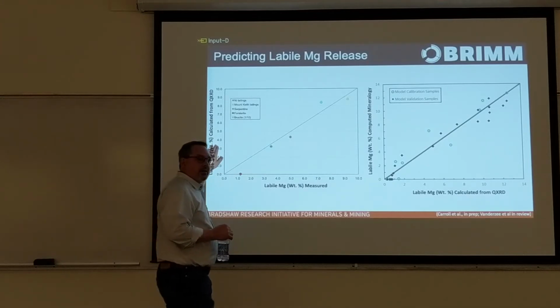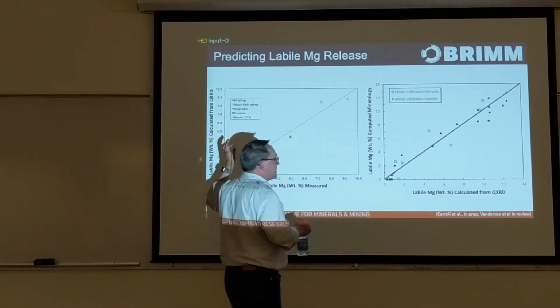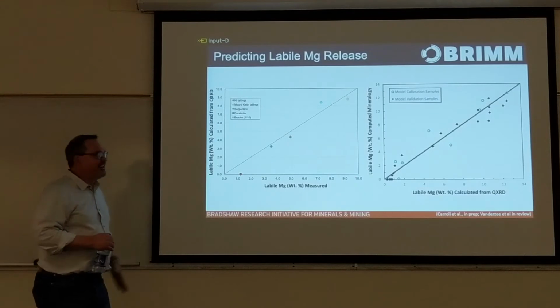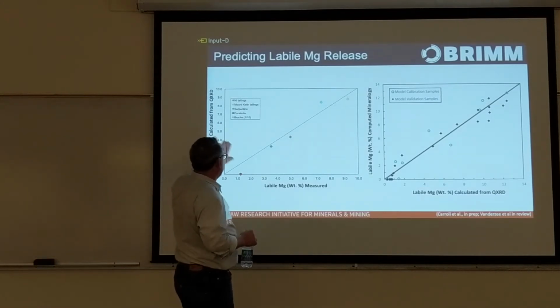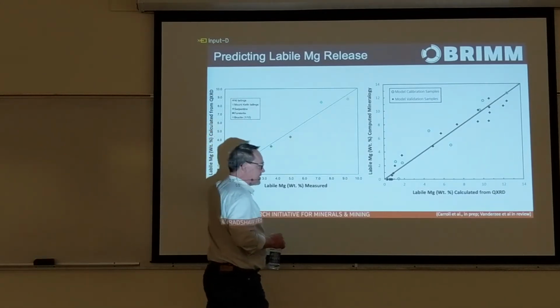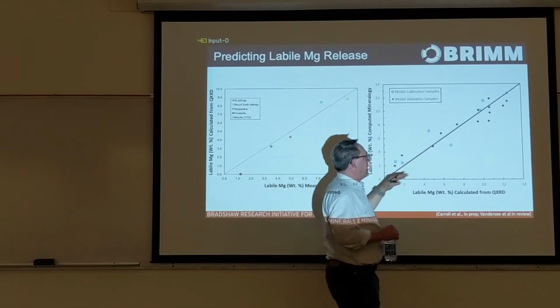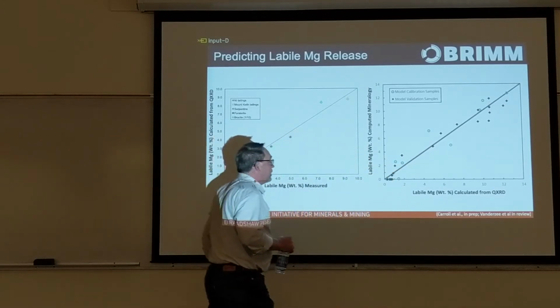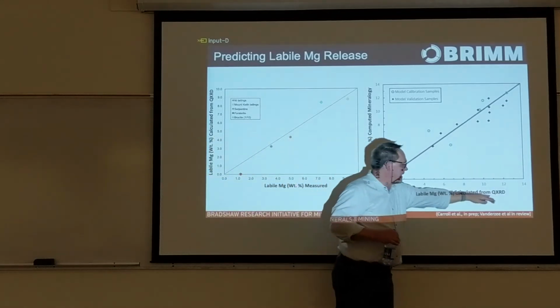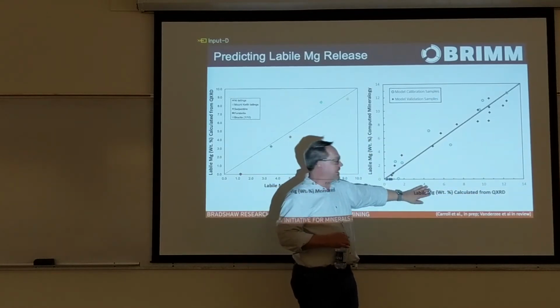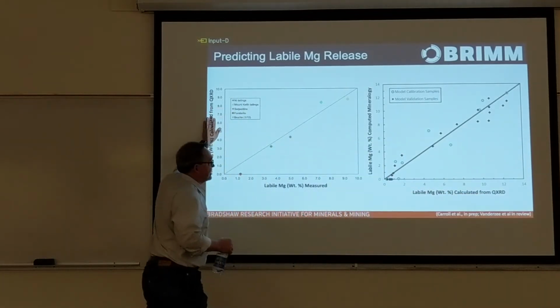That's still hard work, and Maddie's left us, so it's hard to do a QXRD, quantitative X-ray diffraction, to get those mineralogical abundances. This is work that Sterling Battersby is doing for his thesis. Here we've calculated the labile magnesium from the quantitative X-ray diffraction data. So this axis is equivalent to this axis.